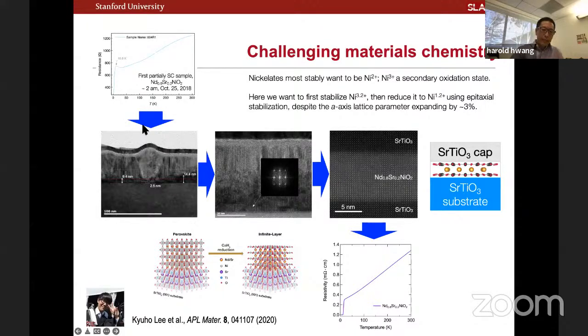And if we look at this generation of samples, what we find is this was our perovskite nickelate. We tried to reduce it. And most of what you're seeing is completely second phase decomposition products. It's kind of a mess, actually. And just at the interface, there's a sliver of what eventually we could identify as a superconducting phase. That is this infinite layer structure.